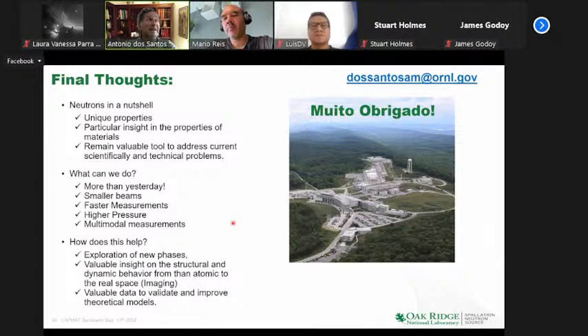We do magnetic PDF. So if it doesn't really coalesce with a Bragg signal, but you are just trying to see the local magnetic exchange. Like I've worked some with people in Porto on Griffiths phases, like some nano domains that don't really develop into a full-on magnetic structure. You can do that from magnetic PDF. So I know it's a lot to unpack in my answer, but it was a big question too. So I hope I answered a little bit.